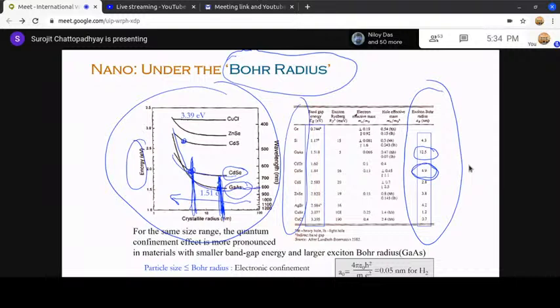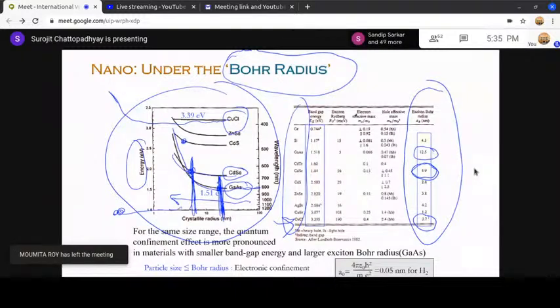Now, for the students who hope to do a PhD in nanoscience, consider copper chloride. Copper chloride is the topmost plot, because if you look at this plot, the copper chloride property doesn't change at all. Let's see where the copper chloride Bohr radius is. Copper chloride is the last one, over here. You see the Bohr radius? 0.7 nanometer. So where is 0.7 nanometer in this scale? It is somewhere over here, so the copper chloride property will change somewhere over there. But 0.7 nanometer means 7 angstrom. That means if you want to be an experimentalist, you have to make 7 angstrom size copper chloride, which is very, very tough. You can try, but it's tough.